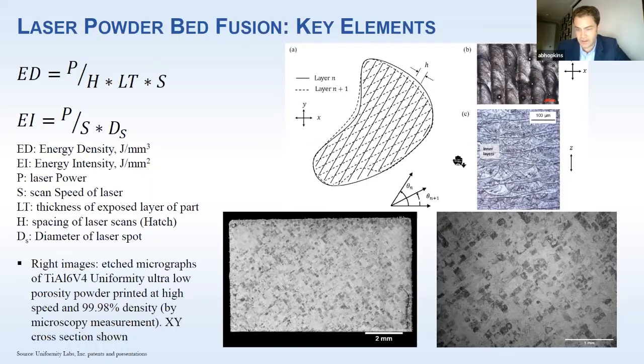So this would be a different scan direction. And on the bottom here, here's some Uniformity Labs Ti-6Al-4V. This is a nice etch of a micrograph. You do get anisotropic properties. This is a cut parallel to the buildup direction, this part. And here's zoomed in here.